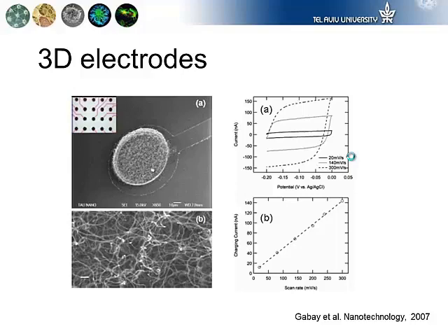These are the electrochemical properties, so just keep in mind that it's a very rough and very robust substrate. And therefore, when you measure the cyclic voltammetry, and try to figure out the electrochemical impedance, or basically the specific capacitance, you can show that it's a very high effective surface area and relatively purely capacitive electrodes.